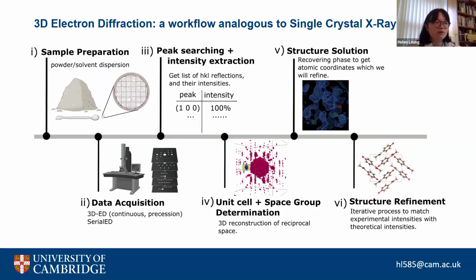So just a quick workflow for those of you who are unfamiliar. This is quite a standard crystallography workflow. You might prepare your sample. In the 3D ED case, we're not having to make any particular effort to grow our crystals. So often we might just disperse the powder onto our carbon grids. We put that into the microscope, we acquire our data.